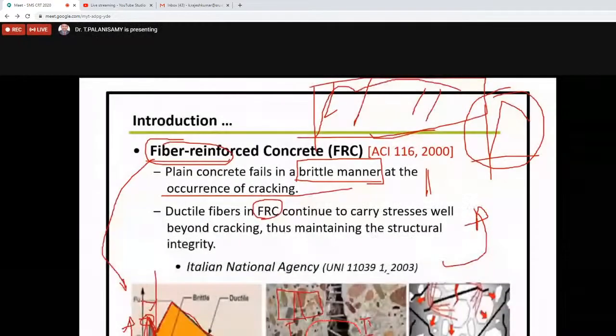In between, we have that aggregate. Even if the aggregate is very strong, for example, you can see this first figure. Look at this middle figure. You can see this is the bridging mechanism. What is the bridging? In between, we have the fiber. It acts as a bridging mechanism between part 1 and part 2. Similarly, the aggregate acts as a bridging mechanism, bridging between two cracks, between the crack openings.